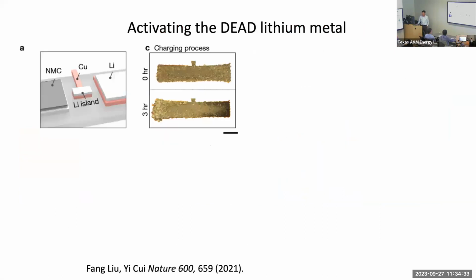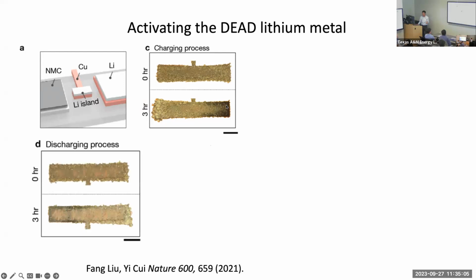Let me look at this. We designed an experiment, patterning a metallic island in the middle between cathode and anode. You see at the beginning, it is golden color, the metallic lithium. After you do the charging process outside, even though this metallic island is isolated, not connected with anything, you see the golden color accumulates to the left. The right hand side becomes darker because those lithium are gone. This is a self-dissolution, self-deposition mechanism. During charging, this metallic island of lithium moves to the left.